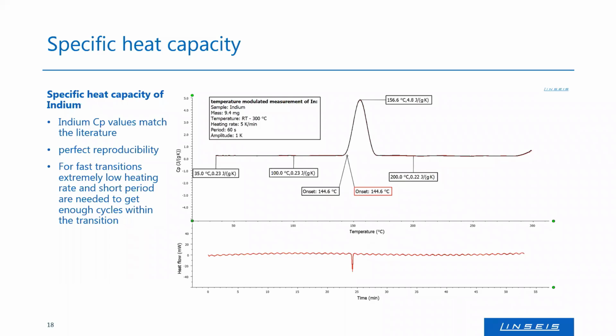So I've tested this with indium. I've measured the indium 3 times, and what you can see here are 2 measurements of this indium. And what we can see here, the reproducibility is quite good. So behind this black CP value, there's also a red one. Maybe you can see it, I'm not sure. So they are really similar. And what's also interesting and makes me quite happy, because I'm the engineer who is responsible for that, is we hit exactly the literature value. The literature says it's 0.23 joule per gram Kelvin, and this is exactly what we can see here.